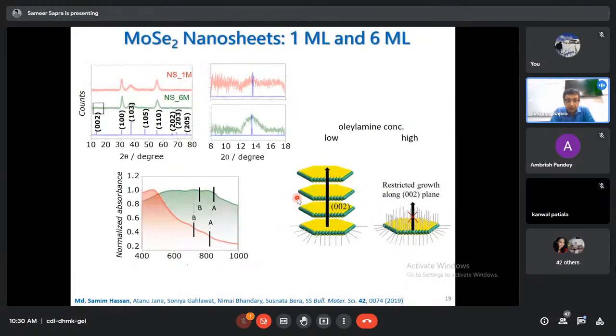But we could do one thing. Oleylamine is the one in which we dissolve selenium, and by changing the concentration of oleylamine we could change the thickness of the sheets. So if you have lots and lots of oleylamine, then it tends to get attached over here very strongly. But if you have less oleylamine, then you don't have it in this direction. It's only in the lateral direction and allows for growth along the 002 vertical direction. Whereas high concentration restricts your growth. So depending on how much concentration you use, you can control the number of monolayers. It's not a very good control, I won't say that, but you can, to a large extent, control.